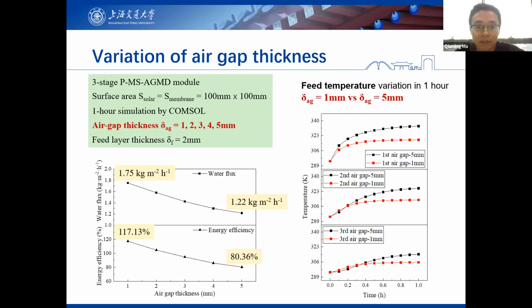And because what we consider it is, I think, about the heat and mass transfer resistance in the air gap. Because when the air gap is thinner, both the heat and mass transfer resistance reduced, and the reduction of heat transfer resistance will increase the conductive heat loss through all the layers. So it's detrimental to the overall performance. But the thinner air gap also ensures a better mass transfer condition. So here we can see from the final performance that actually the thickness of air gap has a more significant impact on the mass transfer.